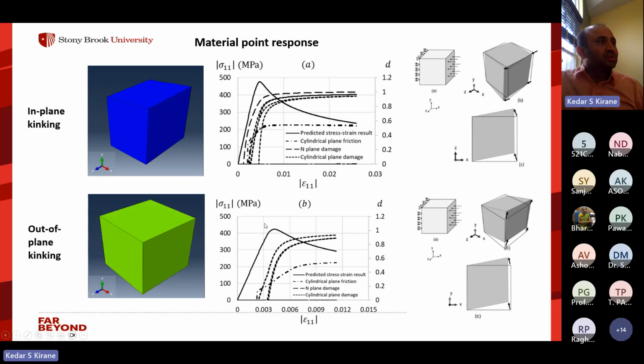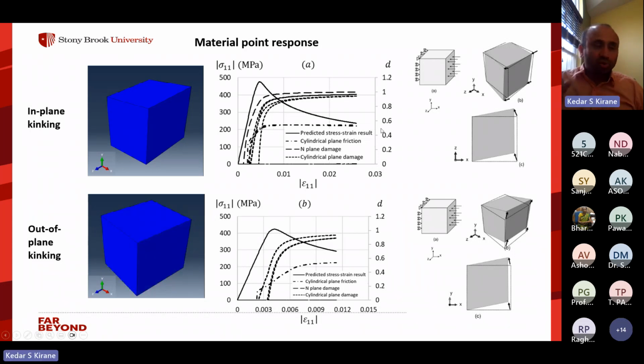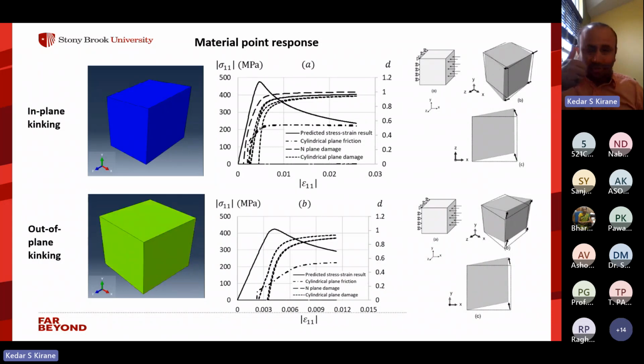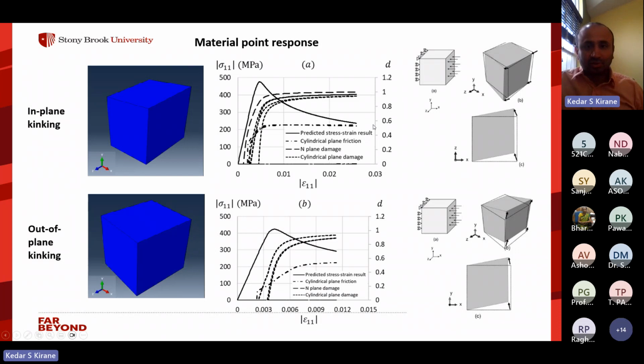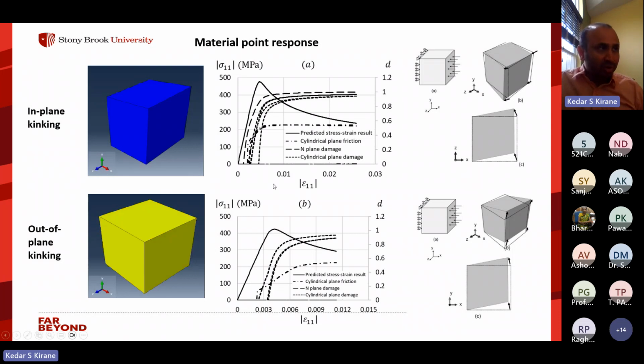Another thing is you can look at the stress strain plot. It goes up, has a peak, and then decreases but doesn't go to zero, it approaches this friction stress and remains constant. So we have local rotation as a result of compression, and we have combined damage and friction, leading to this kind of stress strain plot where the stress doesn't go to zero. So these essentially are the key features of the kink band formation. So that's what we now have in the model.